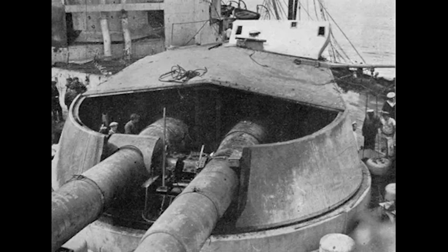circular section of armor surrounding the impact point would shear out and be pushed through the plate ahead of the projectile. Even a badly damaged projectile, its nose deformed and its armor-piercing cap torn away, could follow an armor plug through the plate. The projectile would penetrate in damaged condition, fragmenting as it passed through, but it would penetrate nonetheless. The armor had technically succeeded at Criterion 3, damaging the projectile. But it had failed at its fundamental purpose, stopping the projectile from reaching the ship's vitals.